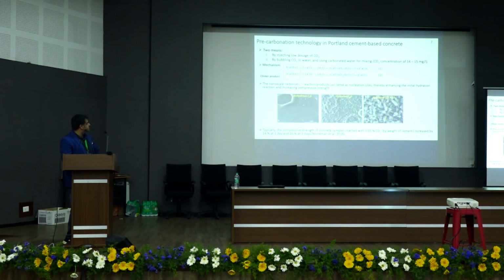So you know that cement has clinkers, right? And it can be tricalcium silicate or dicalcium silicate. And these clinker compounds can react with CO2 that you are dosing into the mixer, and it forms these hydration products and limestone, that is calcium carbonate, right? So if you look at the surface of anhydrous tricalcium silicate, you can see a very smooth surface before hydration starts. When the hydration starts, there are deposits of very small needle-like CSH gel that forms on the surface.